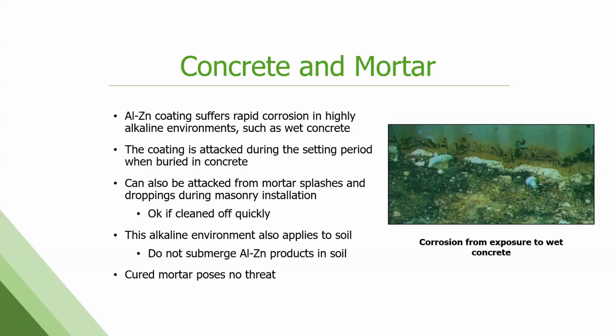Now, if you get splashes of mortar or masonry debris on the surface during construction, they can be wiped off immediately. It's fine. But if you let it sit, it could be problematic. Not only could it stain the surface, but it could cause corrosion. And again, we talked about not putting this product in soil. Don't bury it. Cured mortar, not a problem. Only when it's wet.